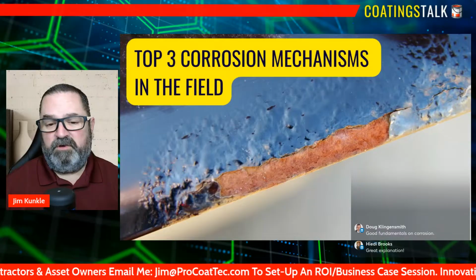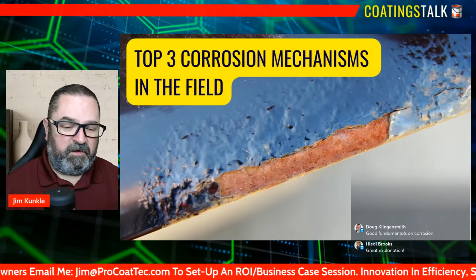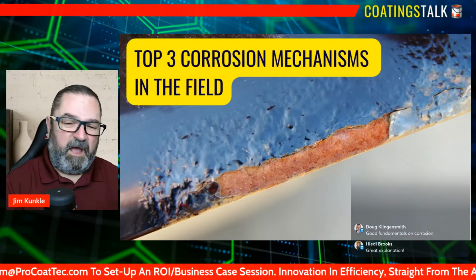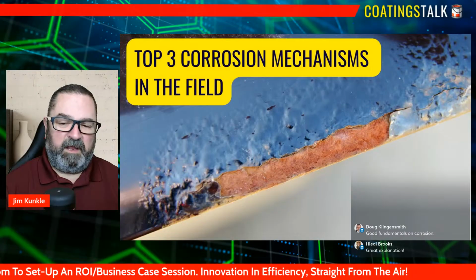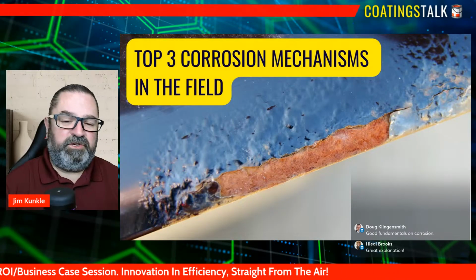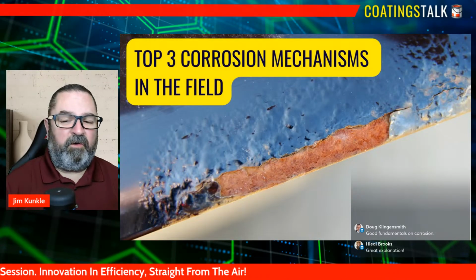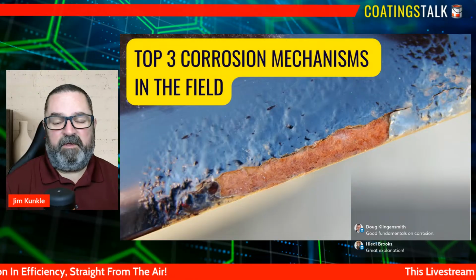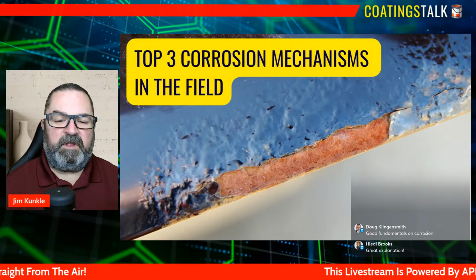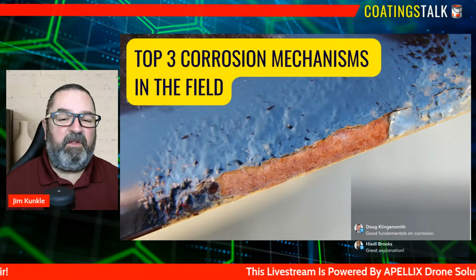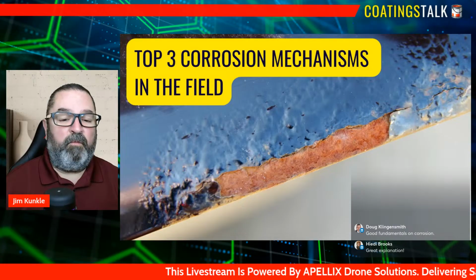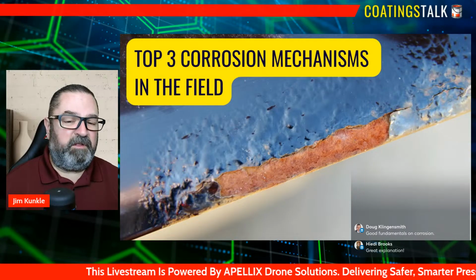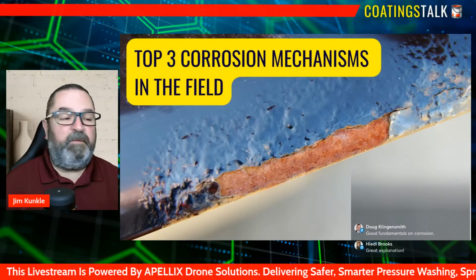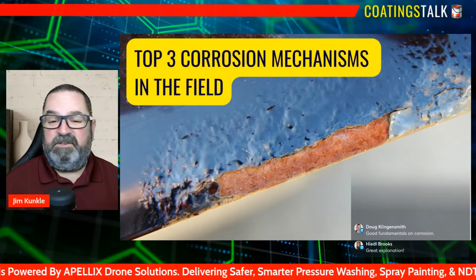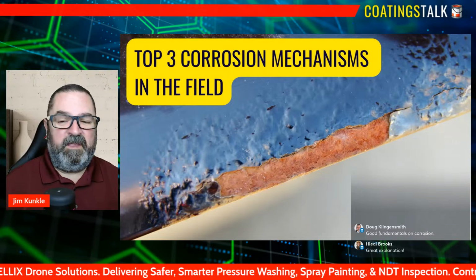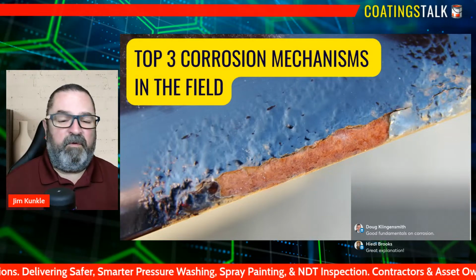Unlike uniform corrosion, which spreads across the surface, localized corrosion attacks in a highly focused zone: tiny pits, narrow crevices, or shielded pockets where moisture, salts, and contaminants become trapped. These microenvironments create aggressive conditions that accelerate metal loss far beyond what the surrounding surface experiences. A component may look healthy from the outside, but just a few millimeters away, a deep pit could be silently eating through the metal.